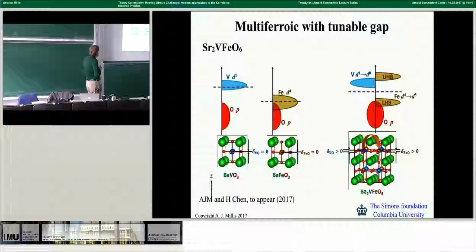He proposed one consider the material strontium-2 vanadium iron O6. So you start with strontium vanadate, which is a material which is a moderately correlated metal like lanthanum nickel oxide with the Fermi level here, and iron oxide, which is actually a Mott insulator with spins. Actually, this is in a low spin state. You then make the superlattice, you get the same level of charge transfer, and now what you have is two remarkable things. First, the iron becomes D5, right? And the vanadium becomes empty.